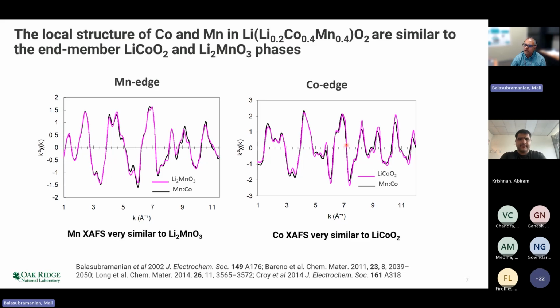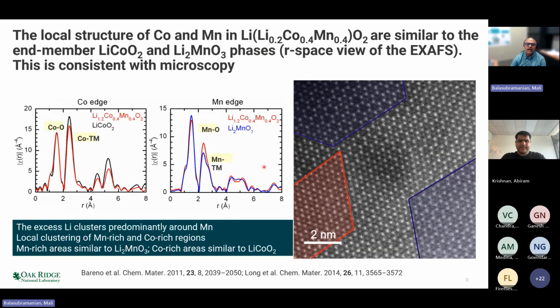Now, if the system was a complete true solid solution on the very local scale, which is completely disordered, then you would expect that the local environment of manganese and cobalt will look identical. However, it is clear from just this comparison that that is not the case. You can do a Fourier transform of this data, and you can come up with the same sort of explanation. What you find here in the Fourier transform again is that the Fourier transform of the cobalt is similar to that of lithium cobalt oxide, while the Fourier transform of the manganese is similar to that of Li2MnO3. So the excess lithium that we are putting, this lithium 0.2, is predominantly clustering around manganese. Local clustering of manganese-rich and cobalt-rich regions is seen.